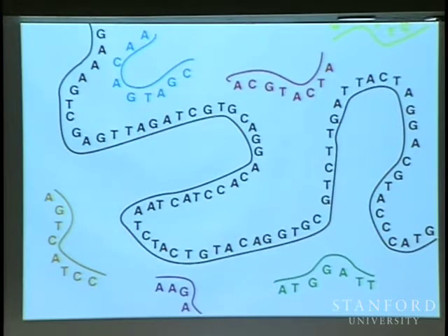And I sent an email to a company. I said, make me 200 of these short sequences. They come in a little box. There are 200 tubes. I mix this long strand with those 200 tubes, add a little bit of salt water, and then heat them up and then cool them down. So you anneal them. That's the basic process.